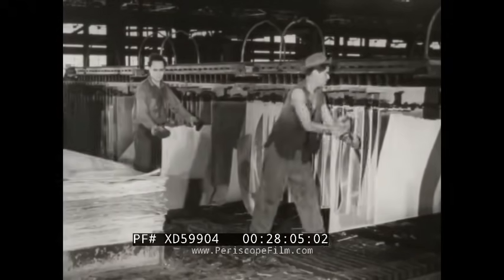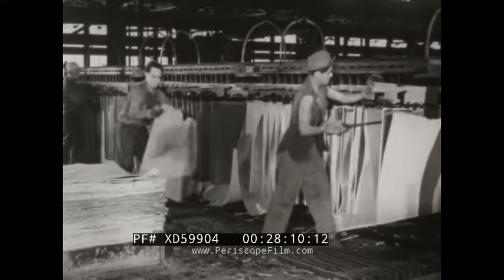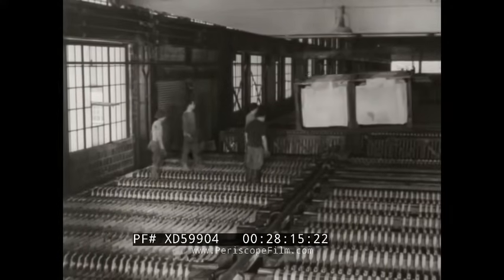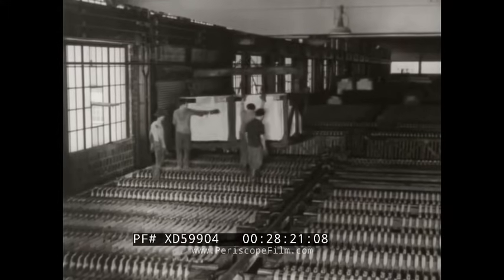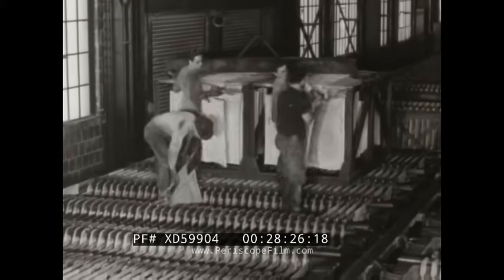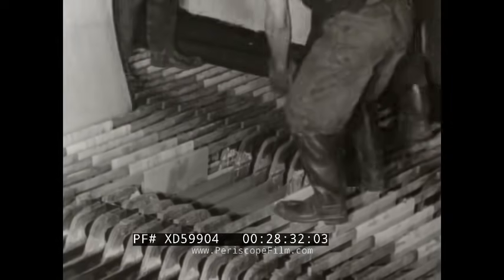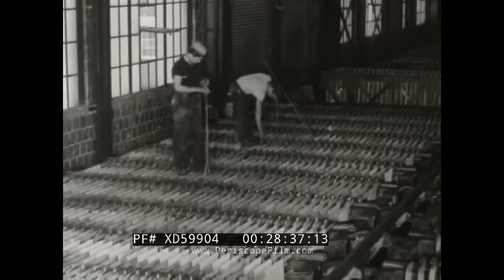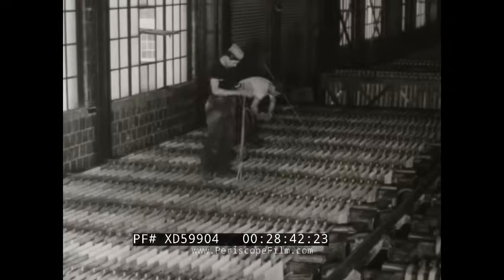These are cathode starting sheets, thin sheets of pure copper electrodeposited on a blank and then stripped off. The starting sheets are attached to copper rods from which they are suspended in the tanks. They are suspended between the anodes on a separate set of parallel bars which collect and carry away the outgoing current. As soon as the electric current is turned on, a careful inspection is made for possible short circuits.